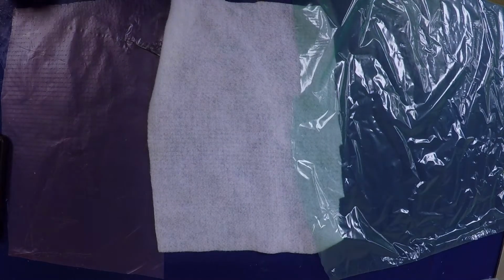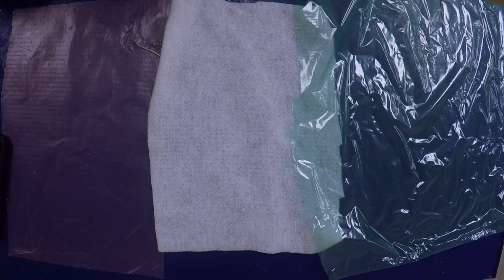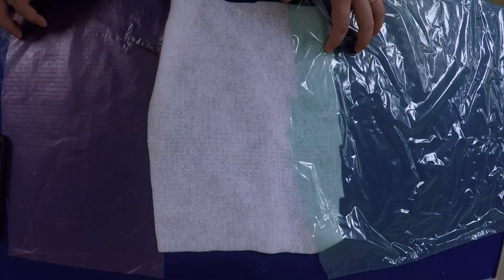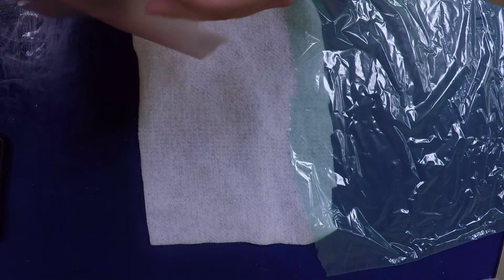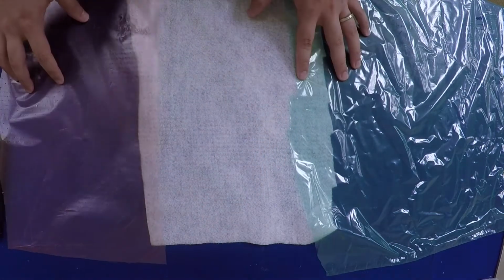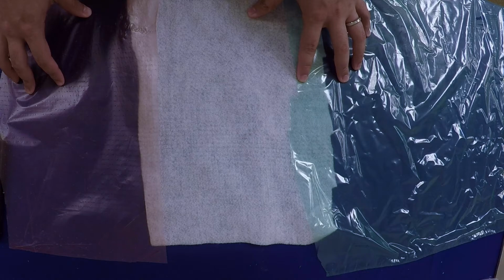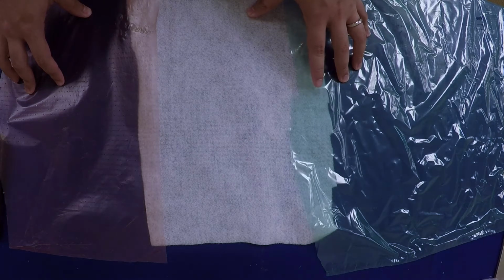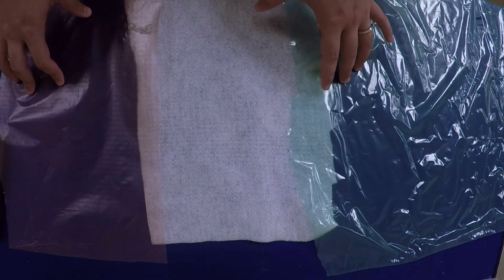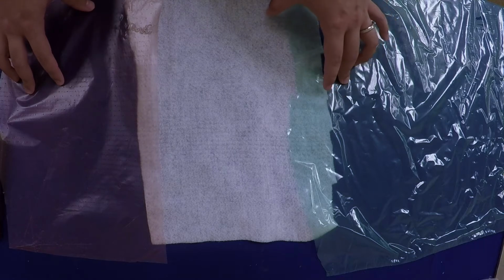The materials needed for the next step must be prepared at least before you begin mixing the epoxy and wetting the fibers. However, it's best if done before even preparing the mold to avoid possibly affecting our release coat. These raw materials need to be cut and sized to our mold to verify proper fitment. Depending on the size and complexity of the mold, this step can take too long, and if done after mixing the epoxy, it will result in having a partially dried product by the time you finish the vacuuming process.